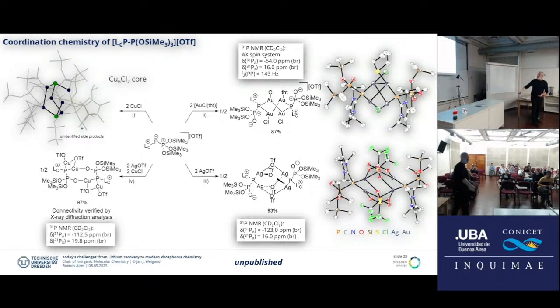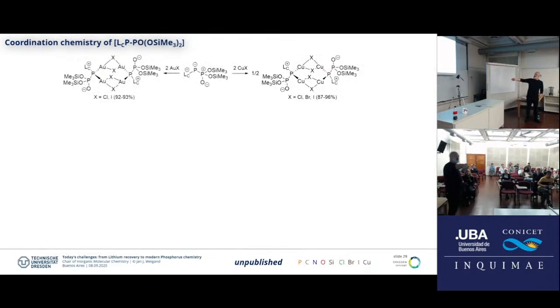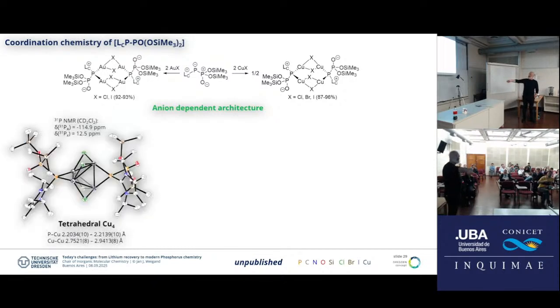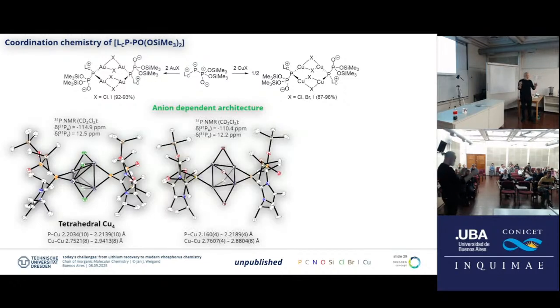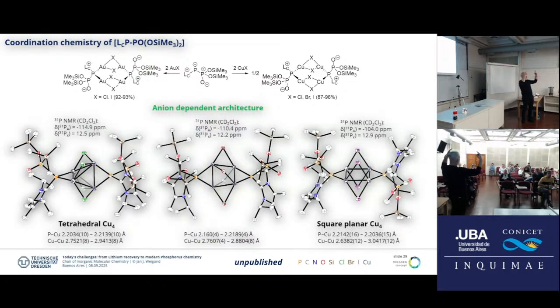Can we prove this further? We can use these compounds, and we now take the one which you've seen before, and react it with gold halogenides or copper halogenides. And what we found out, again from a more theoretical point of view of interest, is that the structures you derive are dependent on the anion. Let's look at the copper ones. So in the case of copper chloride, we get a tetrahedral copper core, where the copper-copper bond modules are bridged by a chloride. If you go to the bromide, we see that the tetrahedron starts to be bent already towards the square planar one. And if you get the iodide one, we get the square planar copper, and we have the iodide on top of it, which is quite interesting. You will see an example in a moment again.